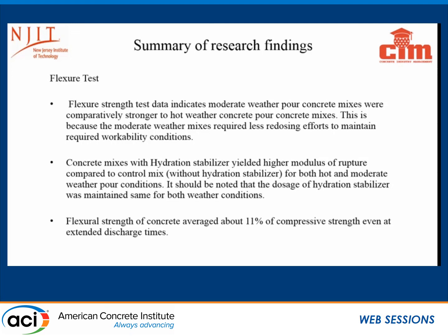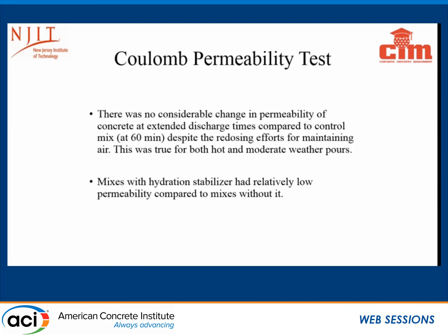I think you asked the question about control mix. Again, the 60-minute sample is the control. Flexural strength was about target, 10-11% of your compressive strength at pretty much all the discharge times. Permeability, as you can see in the previous charts, permeability was good. It was not affected. It was within acceptable ranges. And the ones with a hydration stabilizer had slightly lower permeability results.